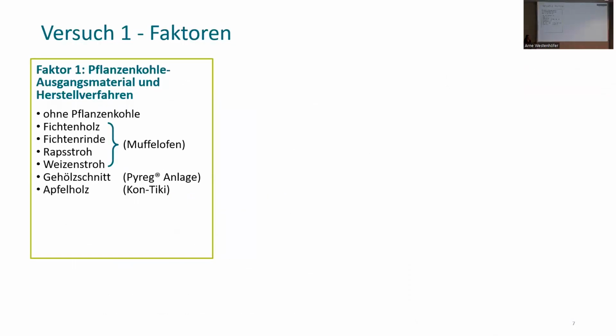Let me get back to the factors, the breakdown. Factor one was the raw material of the biochar and the production material. We had the control variant without biochar. That was the same for the three parts of the experiment. There was a variant with spruce wood, spruce bark, and they were produced by our partner in Aachen, 500 degrees Celsius, and then apple wood from a Kon-Tiki, among other substances you can see on the slide.